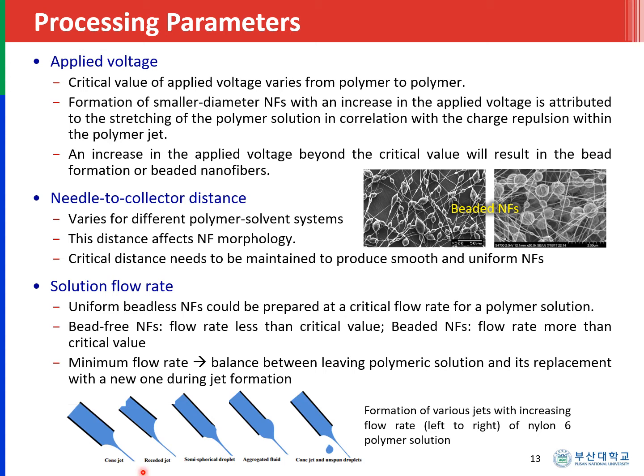If you increase the applied voltage beyond a certain critical value, then bead formation or beaded nanofibers will happen, as shown in these pictures. Beaded nanofibers are considered poor quality fibers. Normally, quality fibers should be uniform and beadless. However, there are some researchers who intentionally produce beaded nanofibers because their target application requires such morphology.